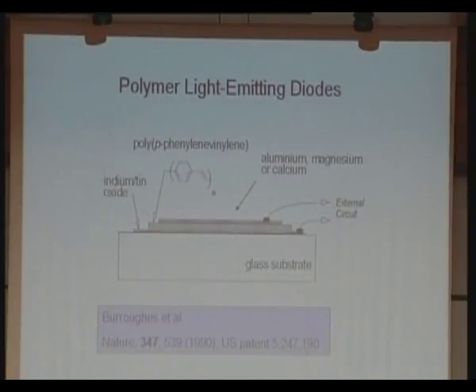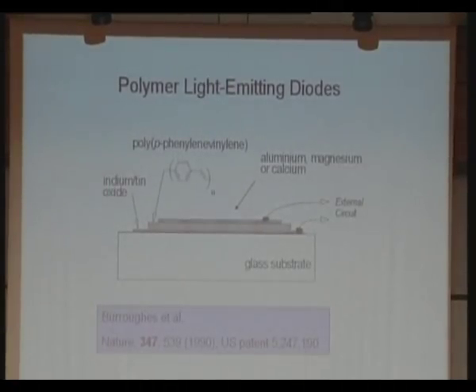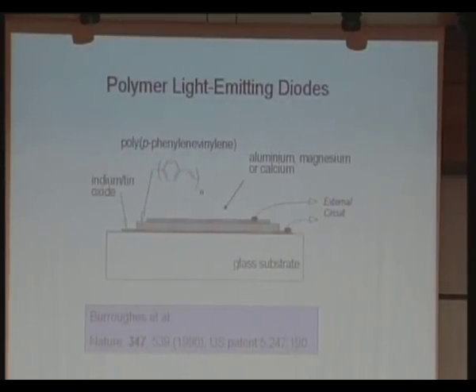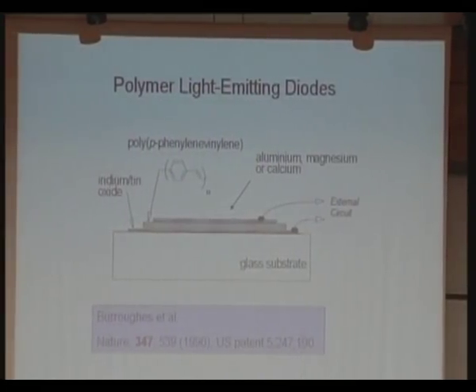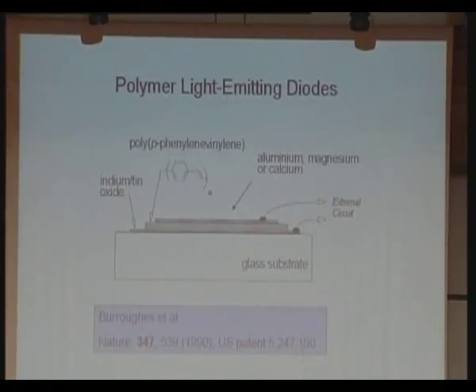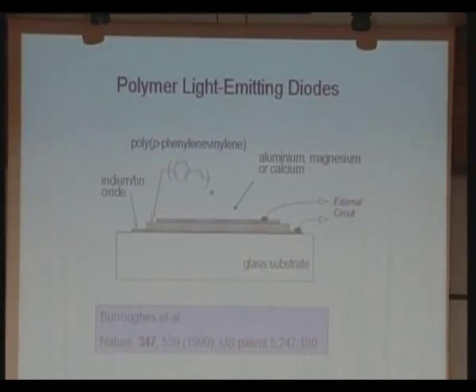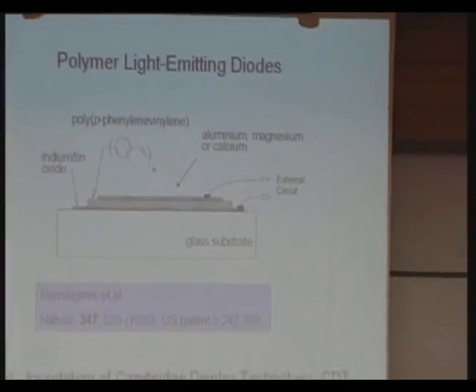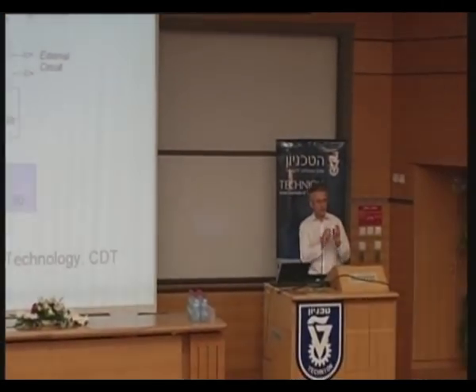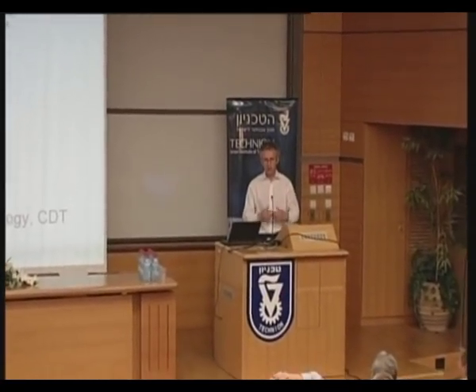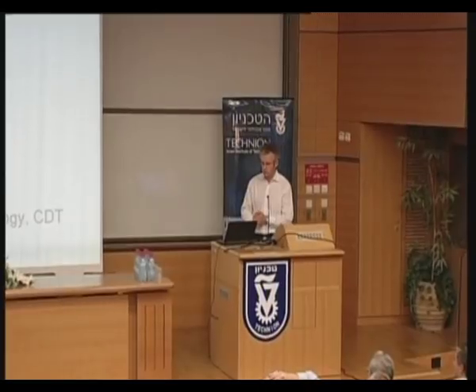What we do is inject an electron from the top electrode and put that into a pi star state, pull an electron out of the low-lying pi state, and as the electron from the pi star state drops down to the pi, that's the radiation, that's the same excitation, de-excitation, as we would have achieved following optical excitation in the fluorescent paint concept. So why these are potentially important is that we can make them wherever we want. We're not constrained to making small devices closely packed together on a wafer of silicon or a wafer of a 3-5 semiconductor, we can literally paint or print.